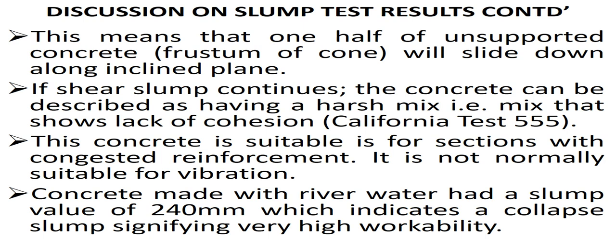This means that one half of the unsupported concrete, that's the frustum of the cone, will slide down along an inclined plane. If shear slump continues, the concrete can be described as having a harsh mix, that is, a mix that shows lack of cohesion. This concrete is suitable for sections with congested reinforcement. It is not normally suitable for vibration.